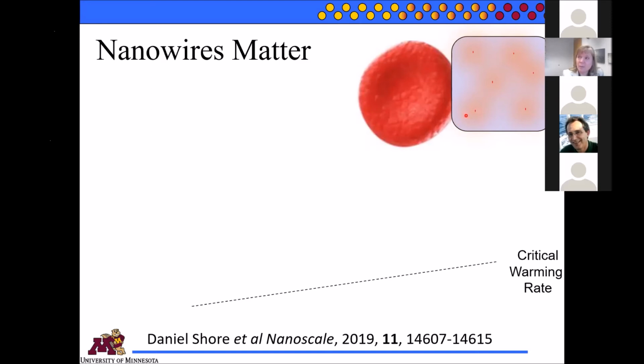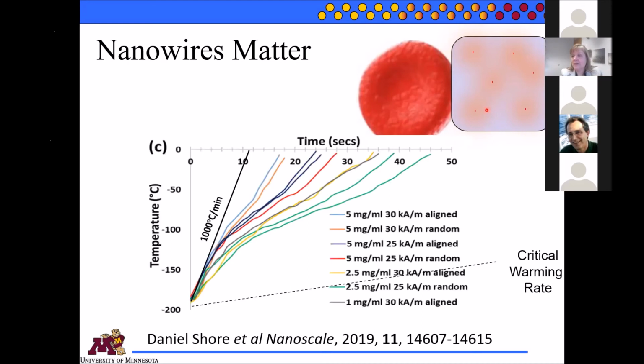And then they warm an area around them. So the key is to get the concentration low enough that they're not going to clog, or not even see each other really. That's the other thing to realize: some of these particles see each other and they agglomerate together. So all the coatings that are on the particles are to stop that from happening. Our nanowires have poles on the ends and they don't really agglomerate very easily. And we also functionalize our wires to make sure those ends don't see each other. Anyway, here's how we did.